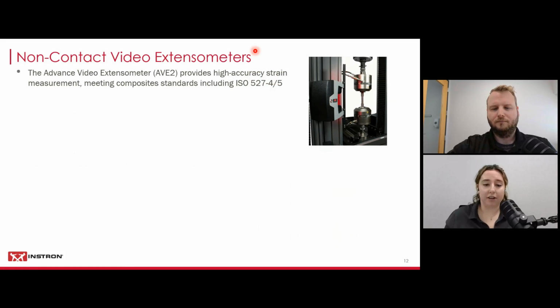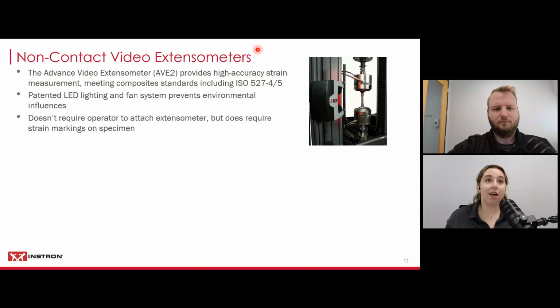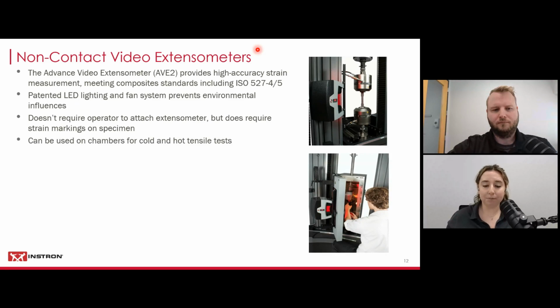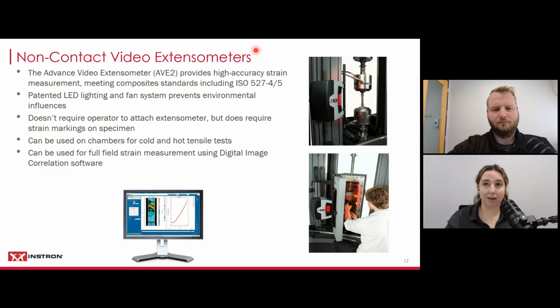Next, for non-contacting video extensometers, the Advanced Video Extensometer, or AVE2, is able to provide high accuracy strain measurements, meeting composite standards including ISO 527-4-5. It has a patented LED lighting and fan system, which prevents environmental influences. It doesn't require the operator to attach the extensometer, but it does require some specimen preparation and strain markings on the specimen for the video. It can be used on chambers for cold and hot tensile testing by attaching to the outside of the chamber. And then it can also be used for full field strain measurement using that digital image correlation software, or DIC. And I'm going to let Stefan talk about that next.